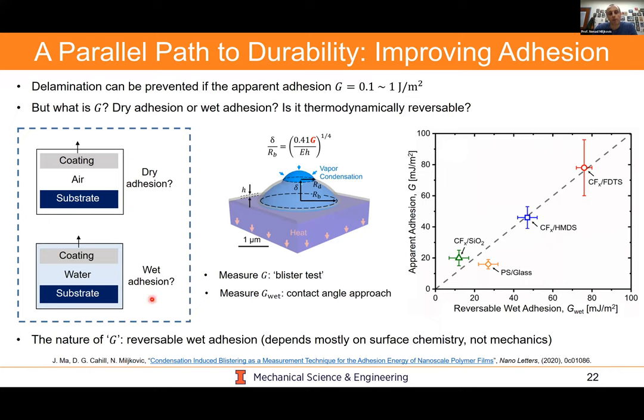What you actually want is a coating which has very high wet adhesion, because what you want to do is what lipid bilayers already do in nature. They prevent water penetration between the substrate and the coating by making a hydrophobic interface, thereby energetically not allowing the water to come into the crack and not allowing the blister to form. This is very important because the relationship between the blister height and the blister radius is heavily dependent on the adhesion to the coating.